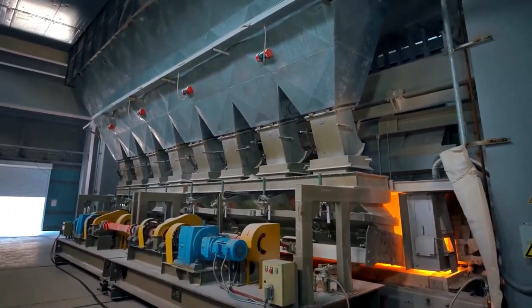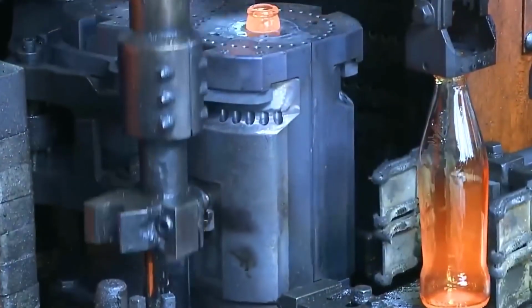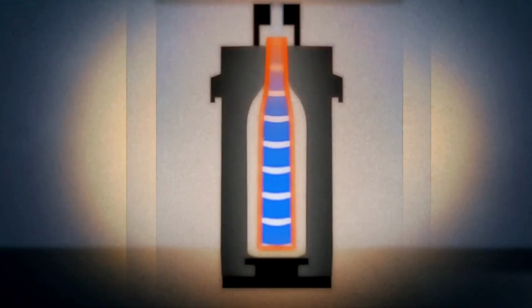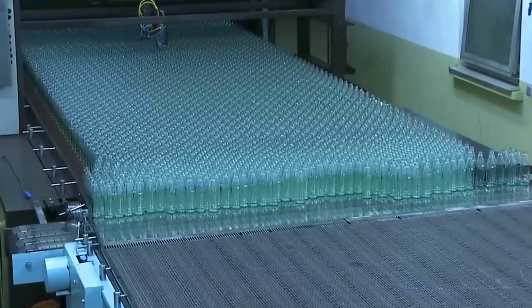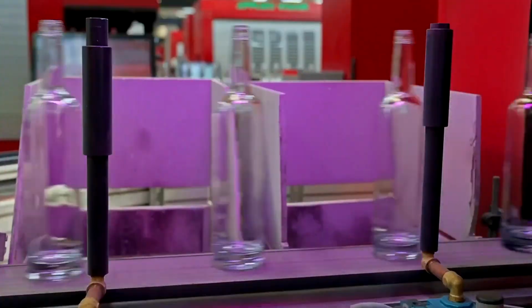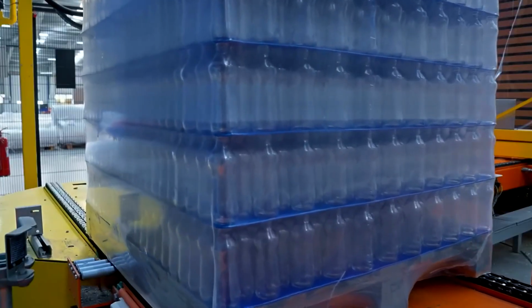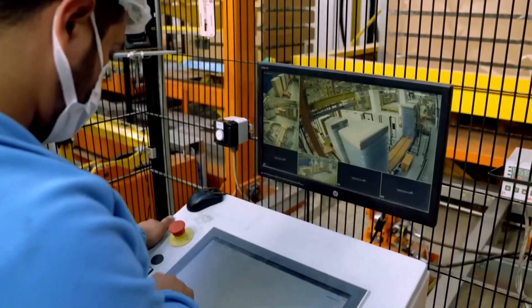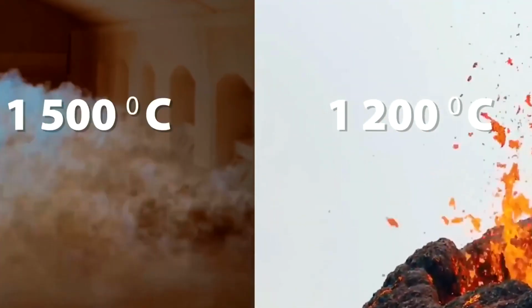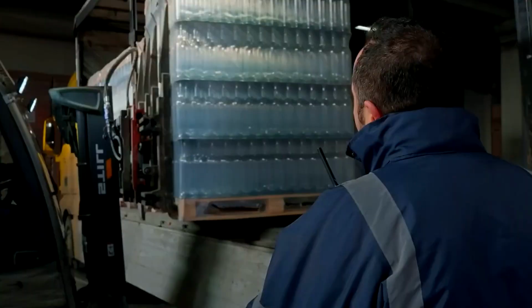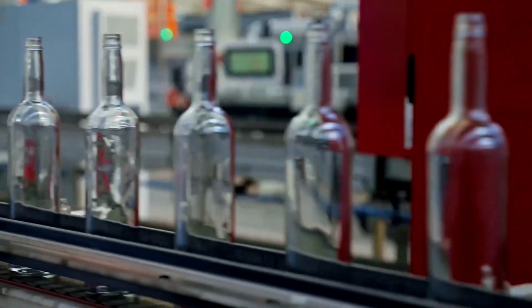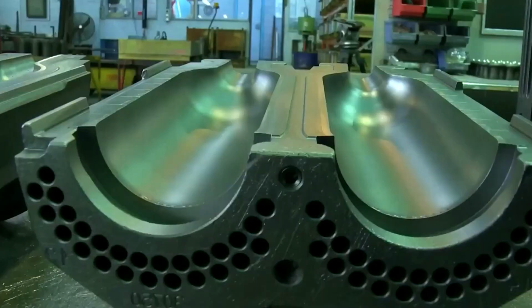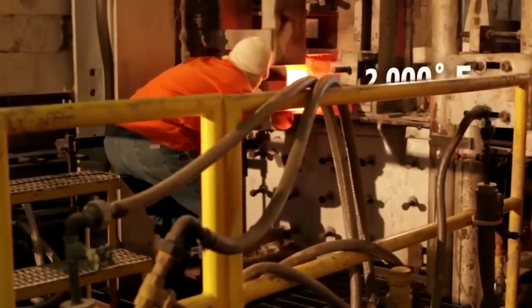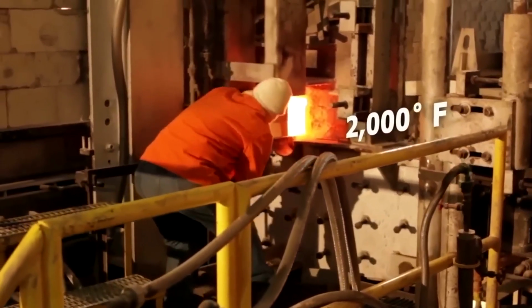Here, the air itself shimmers with intensity, forcing workers to be clad in fireproof suits and Kevlar gloves to withstand the overwhelming heat. Over the course of 24 hours, a profound transformation occurs. The granular sand is gone, replaced by a substance that flows with the viscosity of lava. What glows in the furnace is now liquid glass, a dense, radiant mass that has reached its perfect temperature and consistency. For several more hours, the glass remains in this molten state, allowing any trapped gases to escape and ensuring the absolute purity of the final material.